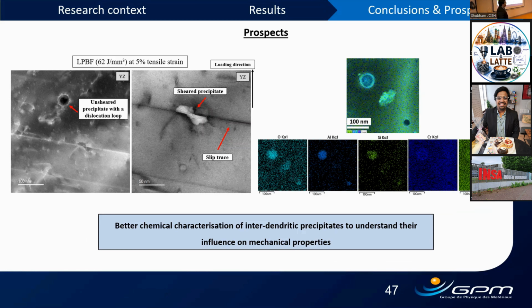No, actually, chemistry was not a big part of my PhD, so we could not have a detailed look at that. But certainly, logically, if we reuse powder, the oxygen level would be higher. So the oxides should be higher. If I remember, it is a contrary effect. But yes, it is quite difficult to analyze. But certainly, what we feel is that right now the most effect is coming directly from the porosities, because the effect of porosities is much higher because of the length scale, or let's say average size. But you don't see too many differences between both batches, if I remember, in terms of porosity. Yes, but also we saw a bit of scattering as well.